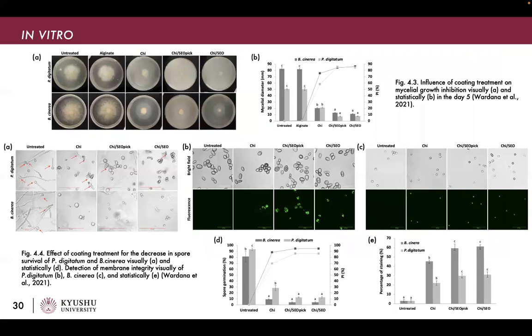As expected, in vitro analysis showed that the coating restricted the growth of fungi compared with the untreated control and alginate representing the commercial edible coating. And there was no significant difference when the cellulose was loaded. There are 2 proposed mechanisms. First, in the study, the use of cellulose was at appropriate concentration as a Pickering agent without reducing the antifungal features of the chitosan essential oil composite.